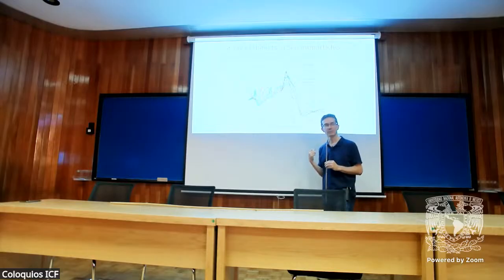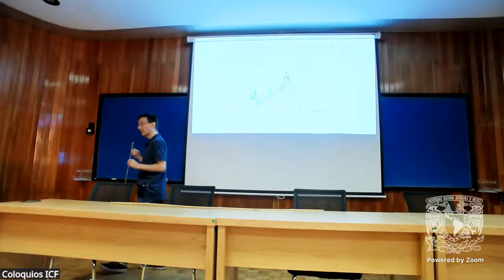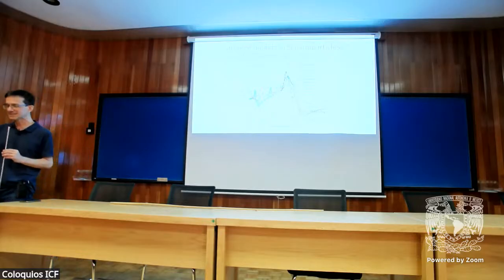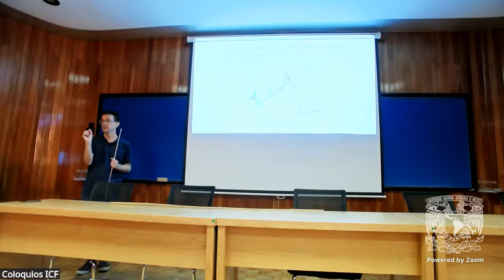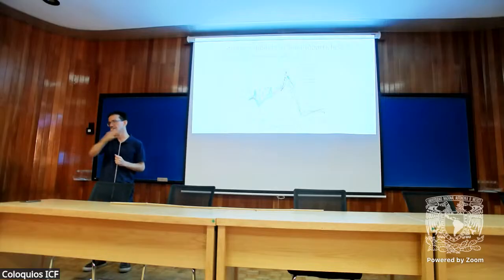The other thing that we can do here also, I only talked about the polaritons, but you have plasmons also. If your sample has the right density of electrons, they will show up here also, the plasmons. This is another kind of study, but they will not be sharp peaks. They will be really broad peaks. So this is another reason to go to the synchrotron, because this kind of broad peak of the plasmons in this region, you cannot do it with laser because it's intrinsically large.